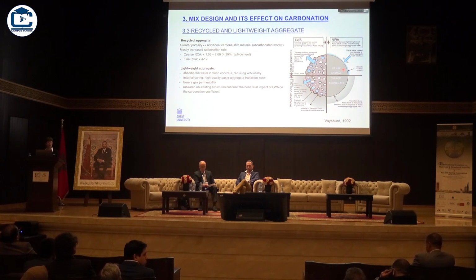What about the use of other types of aggregates, like recycled aggregates and lightweight aggregates? Well, recycled aggregates are mostly found to give an increased porosity to the concrete. On the other hand, there is the factor of the adhering mortar in the recycled aggregates, which may not be fully carbonated, so you have some additional buffering material. But mostly the greater porosity is having the most important effect, and we see an increased carbonation rate if you add coarse recycled aggregates with a factor of up to 2, and even more if you have fine recycled aggregates in the mix.